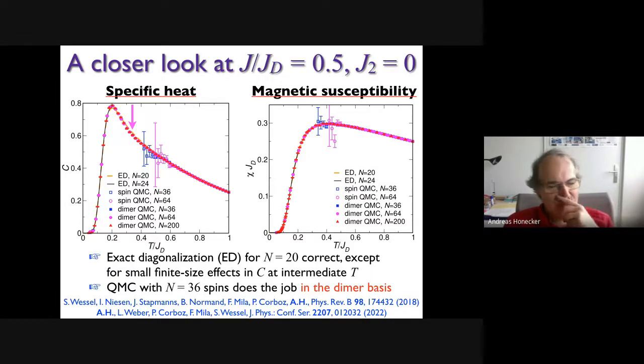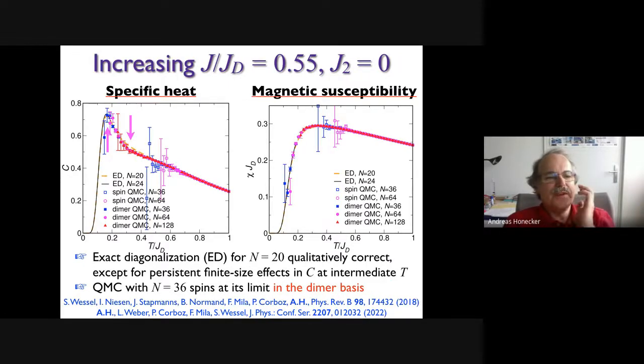The exact diagonalization for 20 sites here is not doing so badly for this ratio, except that you can actually see some deviation at the intermediate temperature in the specific heat here. So if you look very closely at the location pointed to by the arrow, you do see a deviation there. But as soon as you go to 36 spins, you don't see any finite size effects any longer. Right. Now, if you crank this up a bit further,